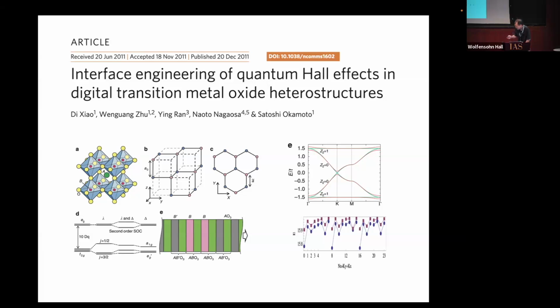So basically, you can regard this as a d orbital version of the Kane-Mele model. And what's interesting about this is that unlike the Kane-Mele model, because it's basically pz orbitals, when you look from the top it is isotropic. The d orbitals are highly anisotropic, and those hoppings can actually give you an extremely flat band, as you can see here. And so our proposal is that if you dope into the system, then it can give you a fractional quantum Hall state, as we showed here.